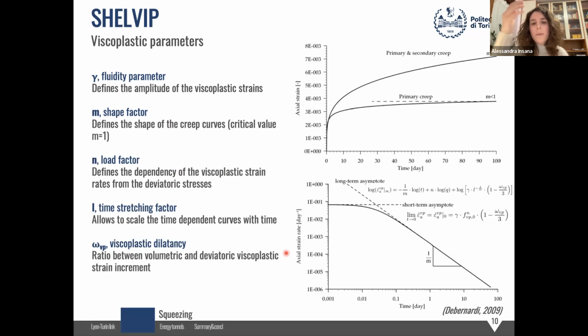This is important because then in the calibration procedure of these parameters, it's important to know their meaning. So gamma is the fluidity parameter, and it defines the amplitude of the viscoplastic strains. m is the shape factor, and it defines the shape of the creep curves. And we see here on the right that the value m equal to 1 is a kind of critical value, because if m is smaller than 1, then we can describe primary creep.